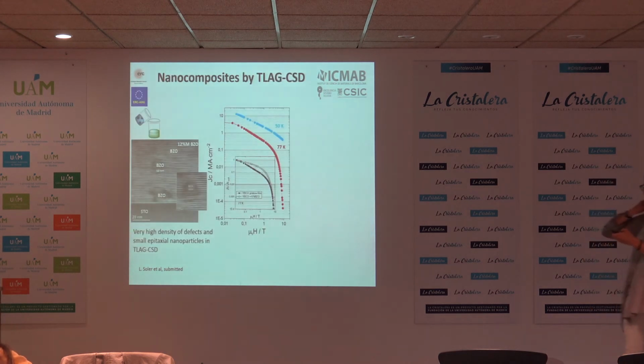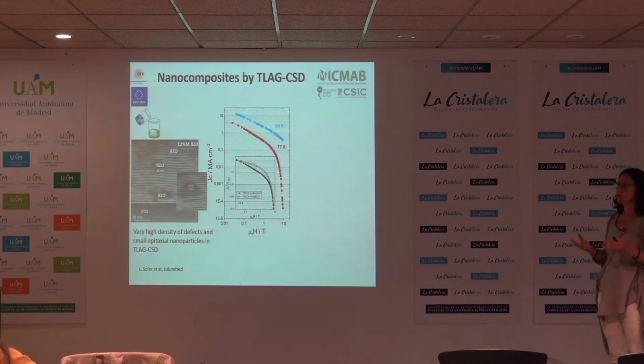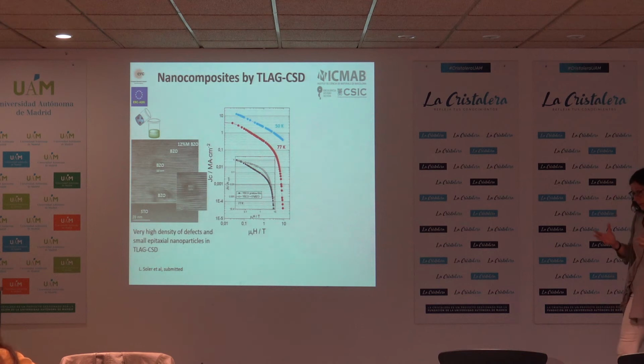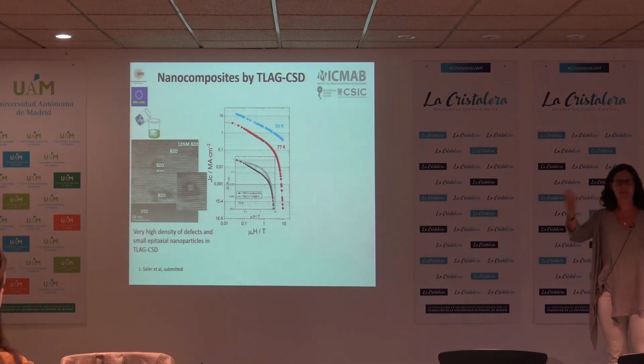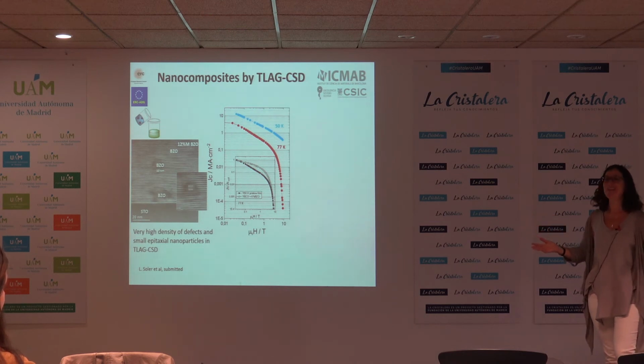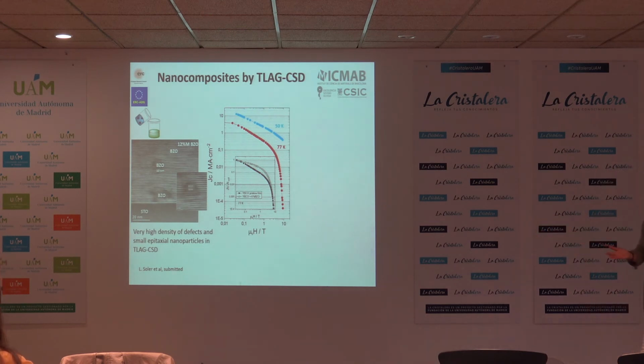But we have also been able to see that this process is compatible with nanocomposites. This is quite important, but it also at the beginning was quite surprising, because you are growing 300 nanometers in 1 to 3 seconds, okay? Are we going to be able to encapsulate these particles, or are all these particles going to be pushed out of the liquid? Are all these nanoparticles going to segregate and deposit onto the substrate?